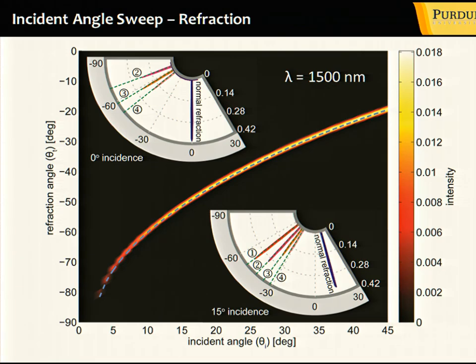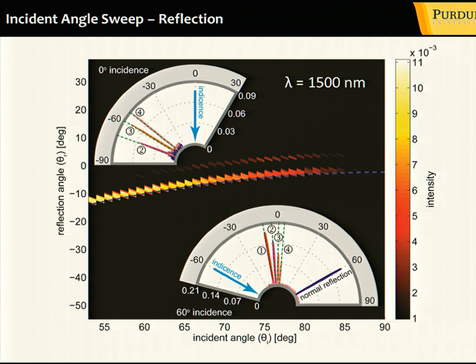So this is our structure, and we showed that indeed you could send a refracted beam in any direction by creating this array of antennas which introduces the gradient of phase, whatever is needed. So we showed it for the telecommunication wavelengths. And you can see that indeed there is this negative refraction, and depending on the period of the structure, the refracted beam could go in any direction you want. This is just different samples. So for one sample with one gradient, it goes this direction, for another this direction, and so on and so forth. And the agreement between this generalized Snell's law, numerical simulation, and experiment is just perfect. So it works just perfectly.